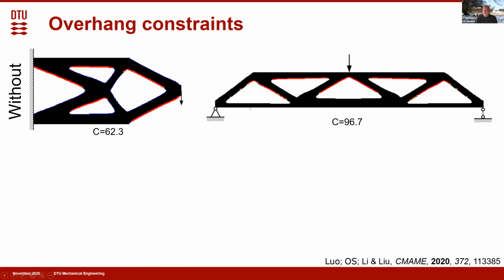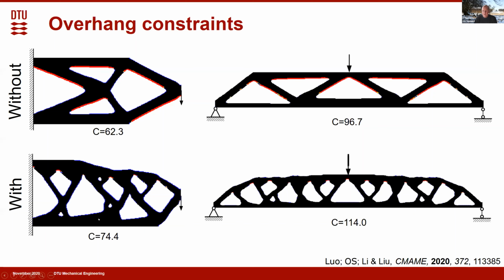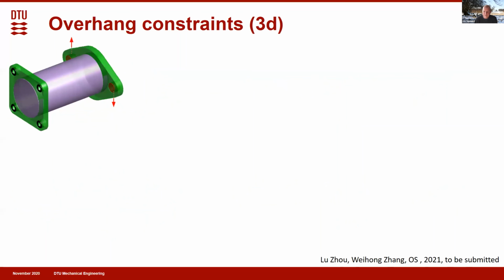This would be two beam structures that are optimized with no restrictions, but we can identify some red boundaries here where you have an overhang that's not possible to manufacture. We can impose a constraint that hinders such overhangs, and well, we will get very different structures. And what we also note is that the stiffness is decreased by 20% when we introduce these manufacturing constraints. So there's no free lunch here. You introduce manufacturing constraints to be able to additively manufacture them, and you lose something on the performance.